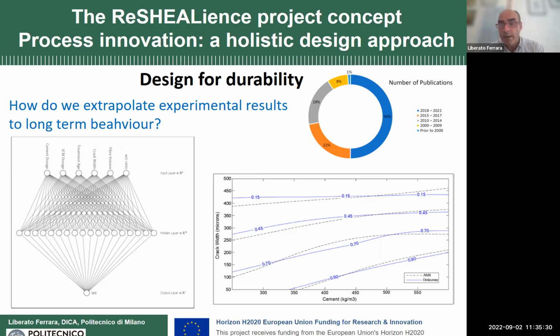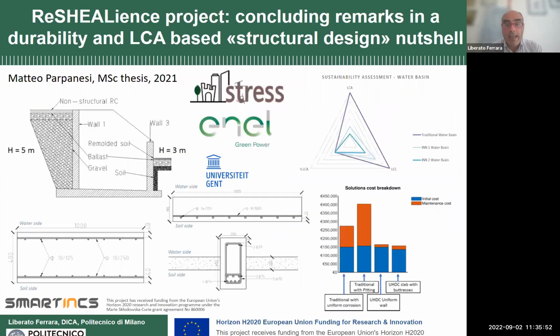in the form of artificial neural networks, developing design cards and design guidelines like the one that you can see here, in which we give the healing capacity as a function of cement content, which is a typical mix design parameter, and crack width, which is, on the other hand, a structural design parameter. So trying always to combine the material and structural design aspects.